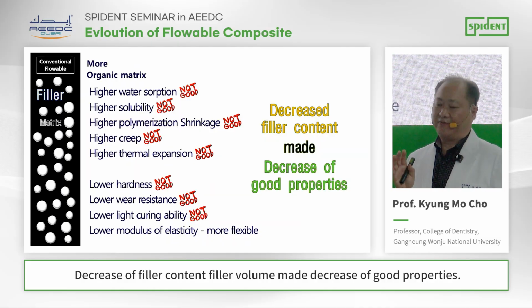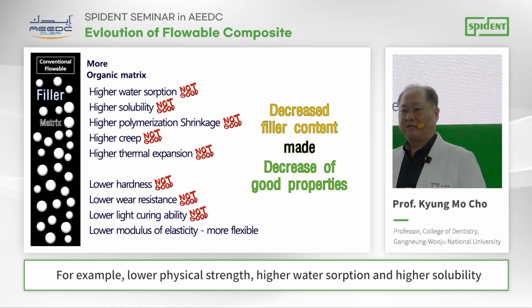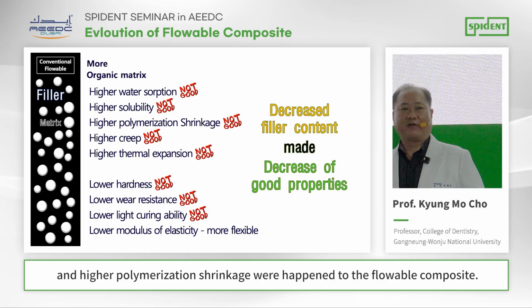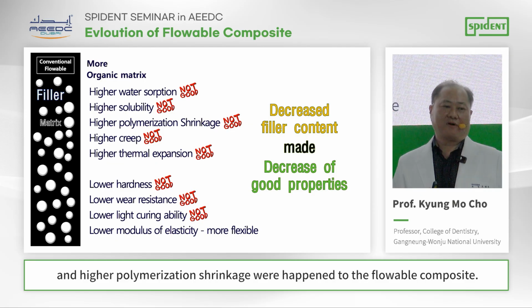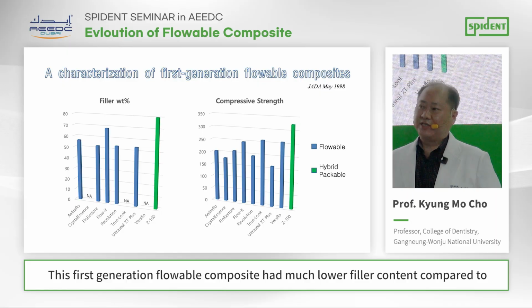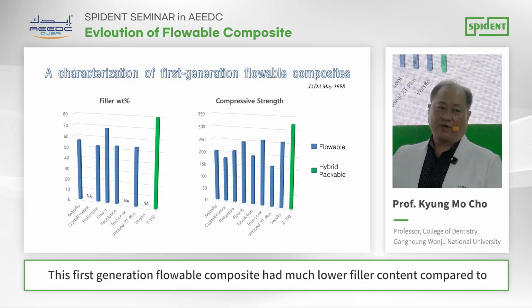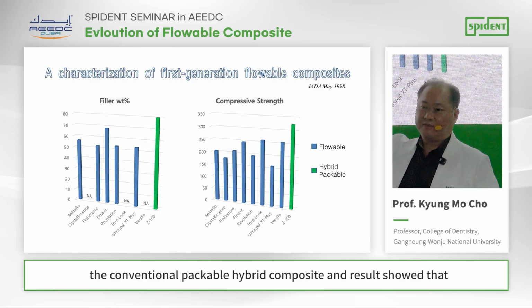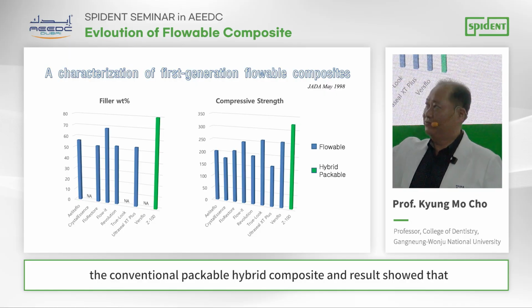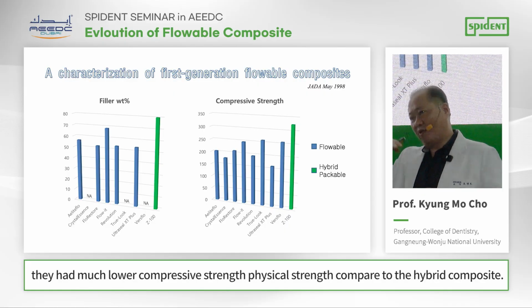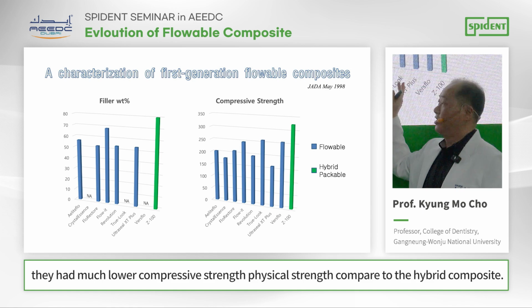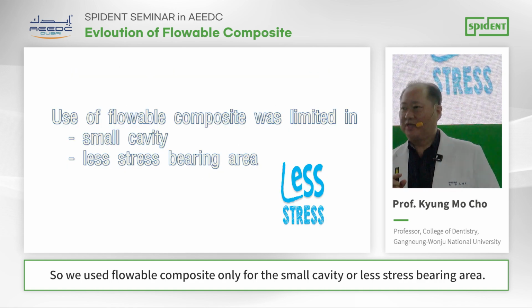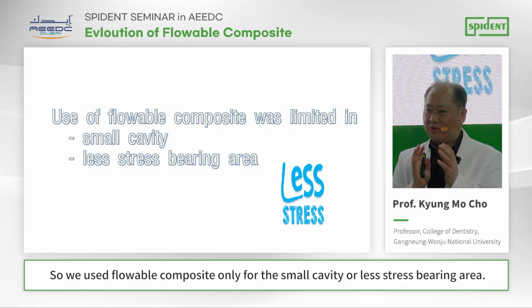But decreasing the filler content and filler volume decreased good properties. For example, lower physical strength, higher water absorption, higher solubility, and higher polymerization shrinkage happened in flowable composite. The first generation flowable composite had much lower filler content compared to the conventional packable hybrid composite. As a result, they showed much lower compressive strength and physical strength compared to hybrid composite. So we used flowable composite only for small cavities or non-stress-bearing areas.